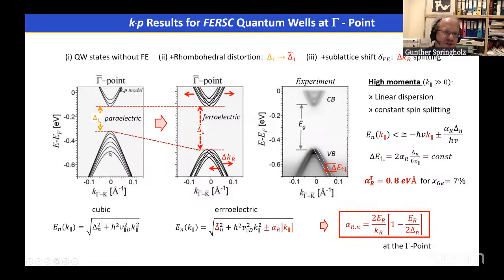These are the electronic subbands, because we have a thin film system, a quantum well system with various subbands. And we see that each subband is split by the Rashba effect. And if we compare this to the experiment, we have again a nice agreement between theory and the experimental results.